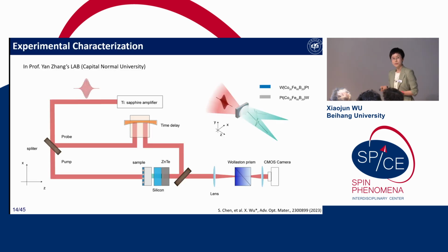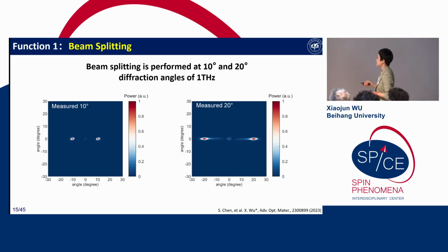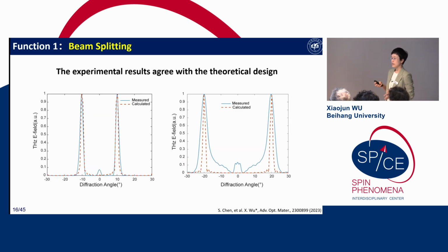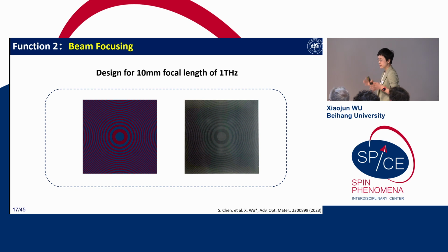So why we do this is that we can get the beam splitting at the source. This is the experimental test. For this experiment, we have to use the Ti:sapphire amplifier, and it is divided into two beams, one directly illuminating the sample, and the other for direct imaging of these two spots. So this is the beam splitting demonstration, and we get a 10 degree diffraction, and this diffraction angle of 20 degree, and this is the experimental result, and the experimental result agrees very well with our theoretical design. Besides, we can just use this spintronic emitter and directly do the beam splitting. So we do not need another metasurface to do that. So it is very great.